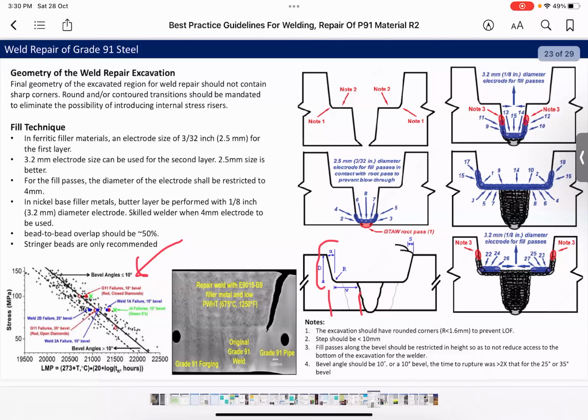So the first pass or the root pass should be done using 2.5 mm. Also, the hot pass can be done using 3.2 mm, but it is much better to use the same filler wire size. And for fill passes, the diameter of the electrode shall be restricted to 4 mm, no higher than 4 mm. But for nickel base filler metals, it is very difficult to do the welding using 2.5.